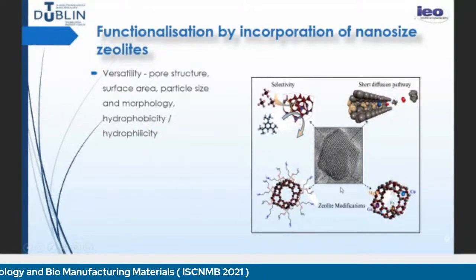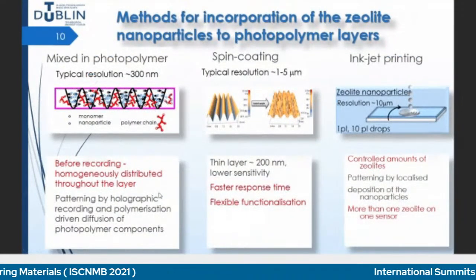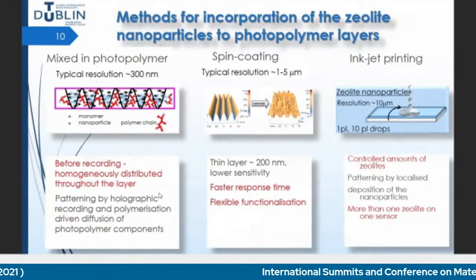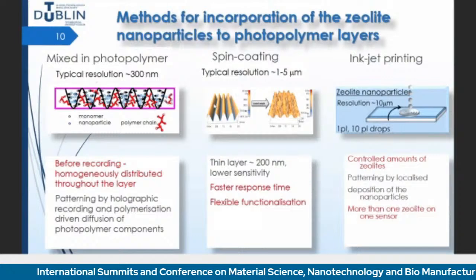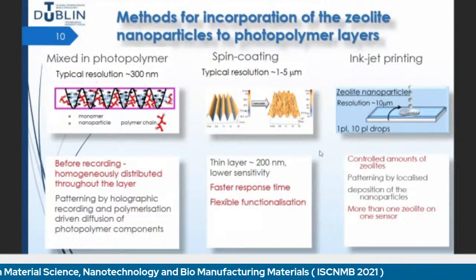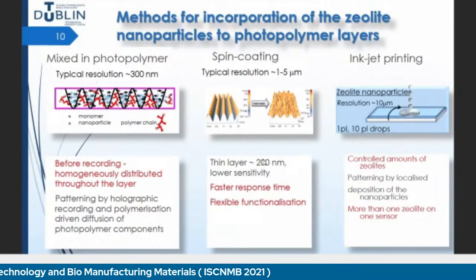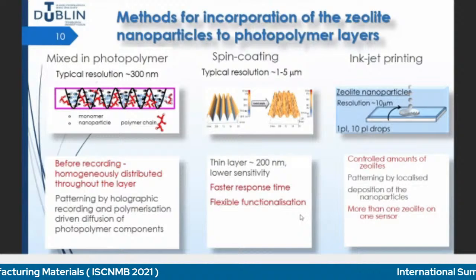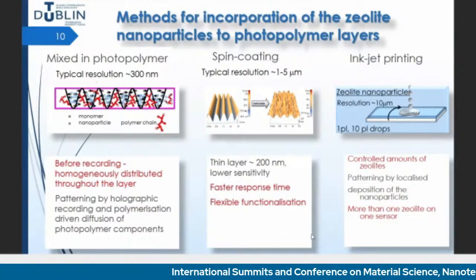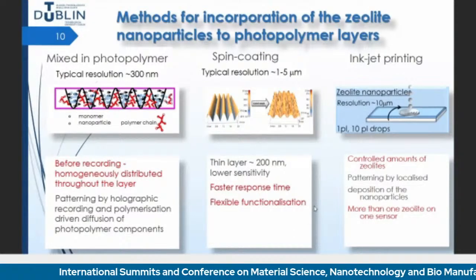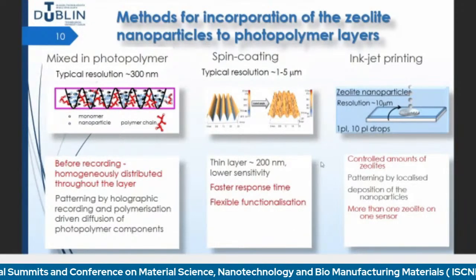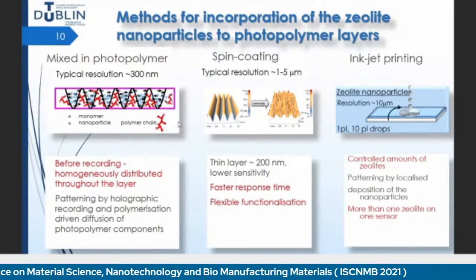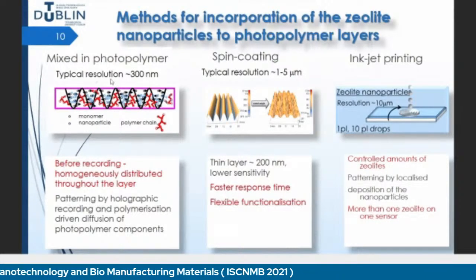They are patterned, so we have a spatial distribution of the zeolite nanoparticles. Another way of adding the nanoparticles to the structures is to first create the structure as a surface relief structure, and then coat it with a nanoparticle layer. These are much thinner layers, around 200 nanometers, and they provide sensors with much faster response time. It's also much easier to functionalize these layers because you just deposit a layer on top of the structure, while in the first case you need to take care of the compatibility of the nanoparticles with the photopolymer